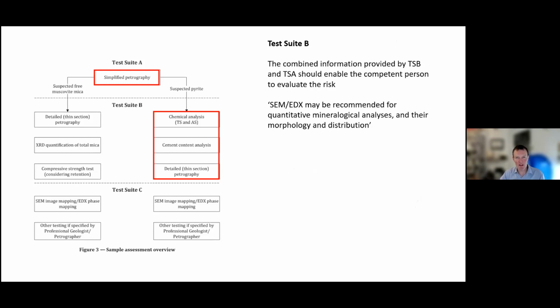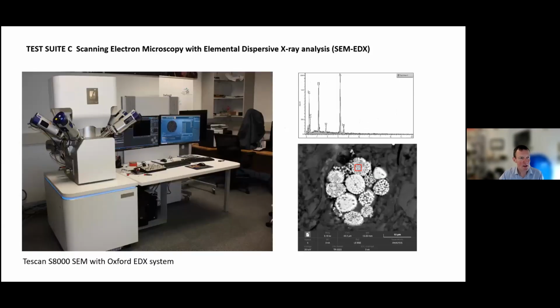In some cases then, it may be recommended that scanning electron microscopy with elemental analysis is used for quantitative mineralogical analysis. So this is the first part of test suite C. Here we have a very fancy electron microscope from Trinity College with big energy dispersive detectors on it. And in the right-hand panel, we have some of this framboidal or raspberry-like pyrite. And we have a little red box that indicates the area that is analyzed above. So this is a conventional way of more or less spot analysis of framboids.